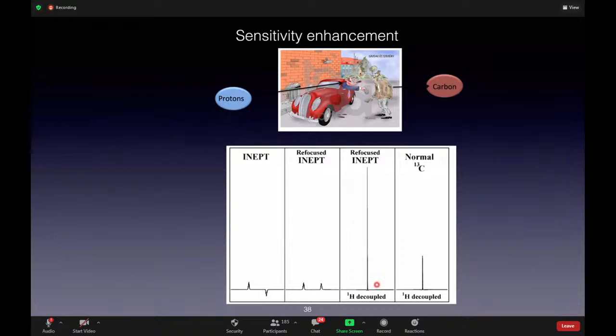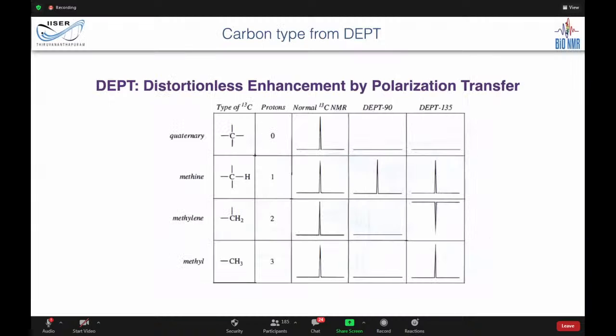And we see that the INEPT carbon-13 signal is much higher compared to a normal 13C signal. That's because the gamma of proton is 4 times higher, and that magnetization is being given to carbon-13 now. So you can increase the sensitivity. This only works if there is a coupling between them. If there is no coupling, there is no INEPT happening. So a quaternary carbon will not give you an INEPT.